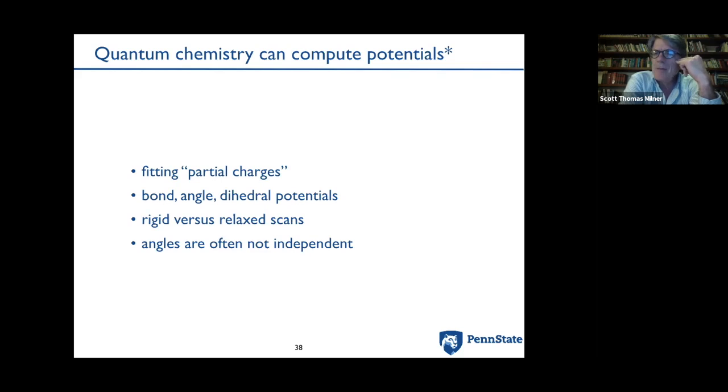The thing I haven't mentioned in talking about potentials that you'd like to compute using quantum chemistry, but you can't really, are the van der Waals interactions. Every nonpolar thing has some polarizability, and two molecules at a distance interact via their dipole fluctuations in what we call dispersive forces or van der Waals attractions.